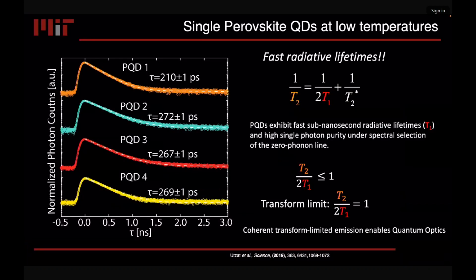So when you cool down a semiconductor material to low temperature, in most semiconductors the lowest state is spin forbidden, meaning that the light coming out is very slow. The lifetime of that emissive state is microseconds, maybe hundreds of nanoseconds, right? When you cool down these perovskite materials, the lifetime is really fast. It's 200 picoseconds. That's really unique, right? There's no other semiconductor quantum dot that has these really fast lifetimes at low temperature.